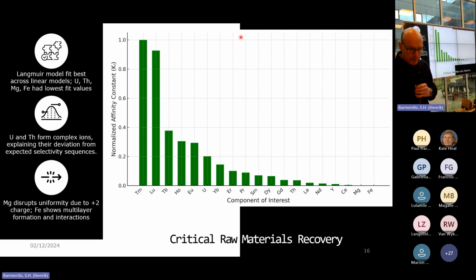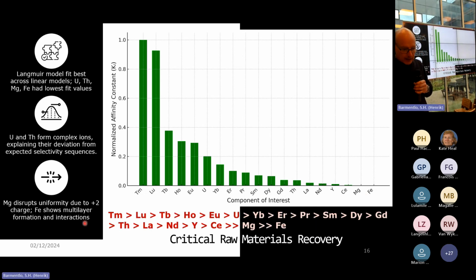So we then said, okay, what are our activity coefficients? How good is this resin at removing this compound? And it turns out it's Tm, which I think is thulium, is the best, and then it goes all the way down to iron. So again, this is good news for us. We want our resin to be selectively stripping out these rare earths in preference to the iron. And that's the sequence. So it's Tm is better than Lu, holmium, europium, uranium, etc., all the way down to iron.